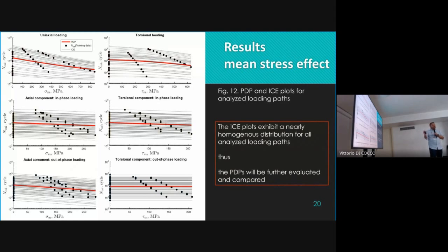And for the last, out-of-phase loadings with the same level of stress values, we can see the impact of axial stresses, but the impact of the torsional mean value for the out-of-phase test was zero. There was absolutely no impact. It might be that we just didn't go high enough with the stress value. Probably we have to test it later, but the line is absolutely flat here.